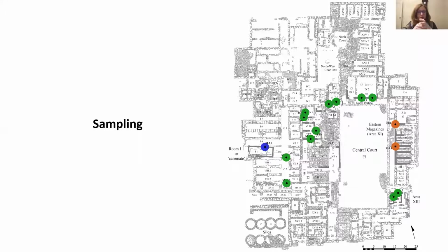For our geoarchaeological analysis, we conducted all the set of analyses that are presented on 15 samples that we collected in situ with a scalpel on the standing wall of the palace. The rationale behind our sample strategy was to collect fragments ranging from the pre-palatial, roughly from the early Minoan 2B period up to the Neopalatial period, so from the early to the late occupation of the palace. We also tried to sample bricks that were coming from different wall typologies, so both exterior and interior walls, and from diverse functional areas within the palace.